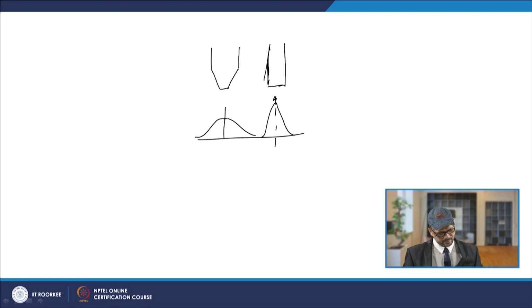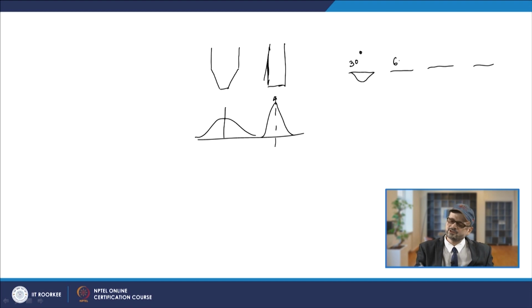Similarly, this will also depend upon the vertex angle of the conical tip of the tungsten electrode. If you change the vertex angle, then as per the observation by Key, if your vertex angle is say 30 degree, the shape of the gas tungsten arc weld will be like this, and if it is 60 degree, the shape will go like this. Then if you have 90 degree, the shape comes like this, and if it is 180 degree, the shape of the gas tungsten arc weld will be like this.